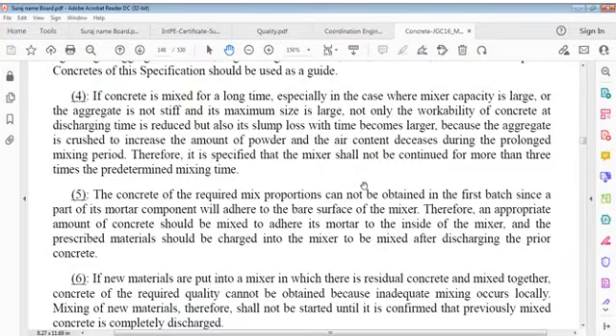If concrete is mixed for a long time, especially in the case where mixer capacity is large or aggregate is not stiff and its maximum size is large, not only is the workability of concrete at discharge time reduced, but also its slump loss with time becomes larger, because aggregate is crushed to increase the amount of powder and air content decreases during a prolonged mixing period. Therefore, it is specified that mixing shall not be continued for more than 3 times the predetermined mixing time.